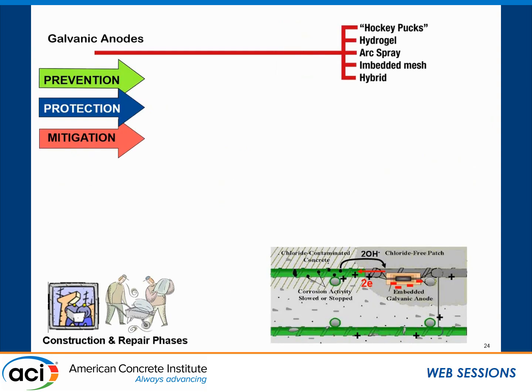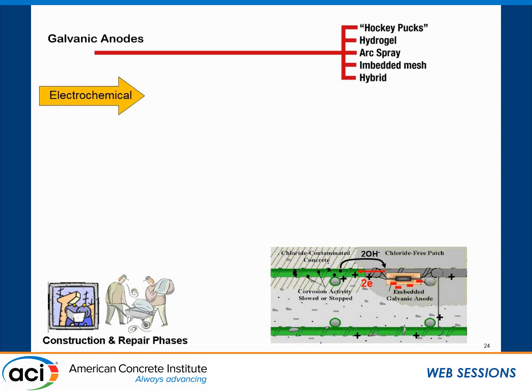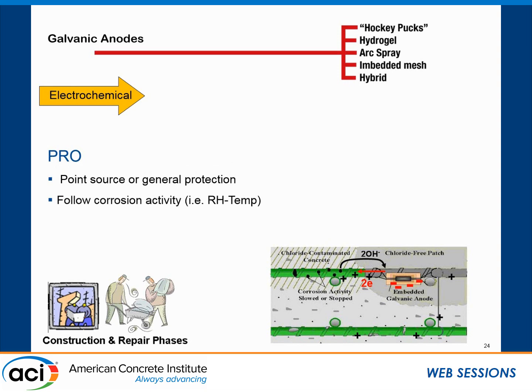There's discrete and there's distributed. These work like galvanizing on steel. So the zinc corrodes preferentially, the zinc is the anode, and the steel becomes the cathode. They're really an electrochemical method. Their advantage, they're a point source, or the distributed ones can be general protection. They follow the corrosion activity, so it's like self-regulating. They don't require an external power supply. As the corrosion of the steel wants to increase, the corrosion rate of the galvanic anode increases to keep up with it, if it's properly designed.